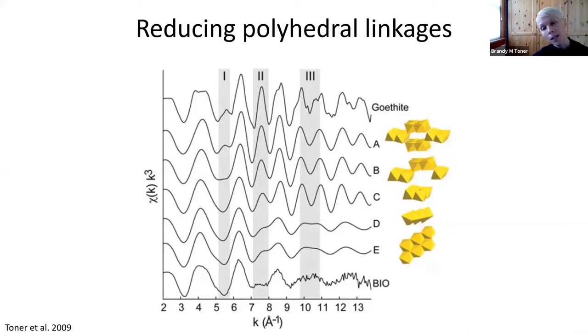But ultimately what we found is that the most consistent model for the biogenic minerals were these two-dimensional sort of blebs of material, very little corner sharing in the polyhedral signatures, very consistent with edge sharing. And so what I have here is this little diagram on the right-hand side sort of representing what the shell-by-shell model was that best fit the biogenic iron oxyhydroxide.